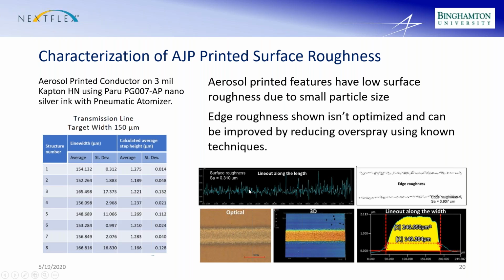And this shows the surface roughness is 0.3 micron. That's typically what you see, and the edge roughness over here is around 0.9 micron. A lot of the edge roughness is from some overspray, which if you're familiar with aerosol jet, when you print a line, the edges are not clean and crisp like etched. There's a little bit of overspray, and this profilometer shows the profile, and there is a little bit of a hump and some trailing on the edges, so that is part of the profile. It's part of the things that you have to design to. So when you get into this, you really want to characterize what you're printing, and what your expectation is of what you're printing compared to an etched copper foil, which you might be used to.